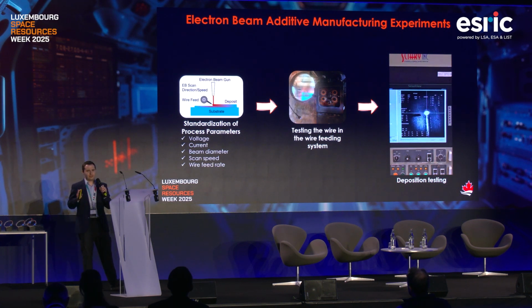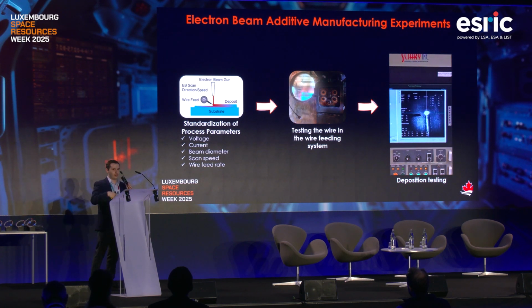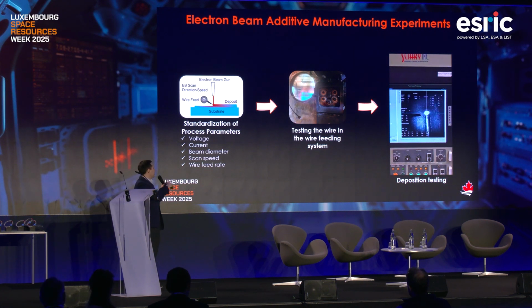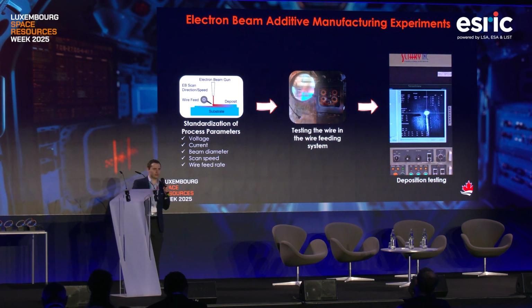Once that had been standardized for some aluminum alloys that we were testing, we used our wire, the one that we had made in the lab. We had to test it because it goes through the feeding system, which uses rollers. Rollers kind of press and pull the wire at the same time. So if the material is brittle or it has imperfections, it might not go through. We tested that, it went through. And after that, we did some deposition testings to see if that's something that would work.